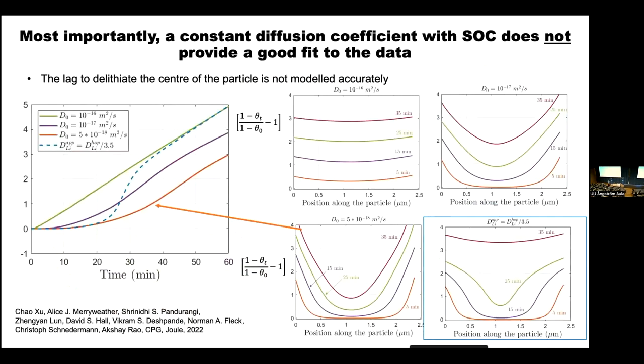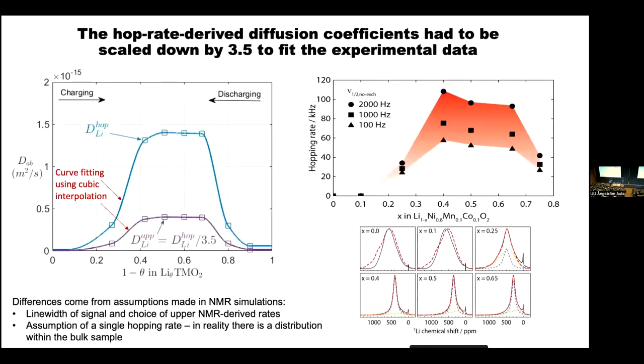As a reality check, if you have a constant diffusion, you don't actually get that same lag phenomenon. These are simulations where we're looking at different diffusivities to show that you cannot model this lag unless you actually have a change in diffusivities as a function of state of charge. I also want to point out that in order to get that fit, we actually had to take not the highest lithium diffusivities that we got by NMR, we had to scale them down by a factor of about 3.5. That was due to a number of assumptions we made in the models, primarily that the NMR had chosen the most optimistic line width to do the modeling.